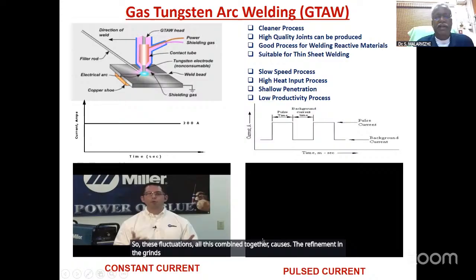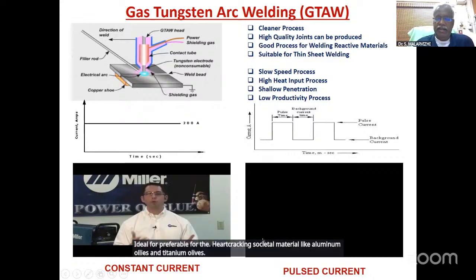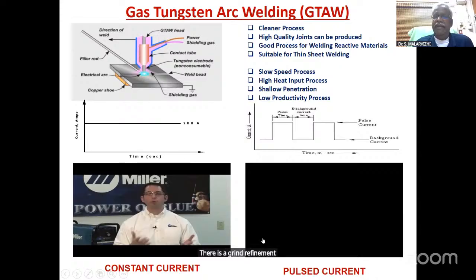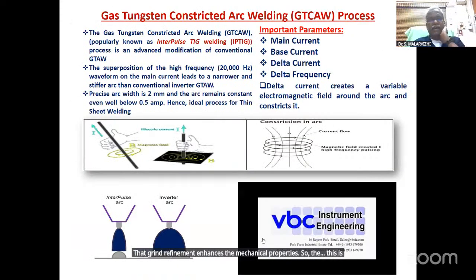So all these fluctuations combined together cause the refinement in the grains. Grain refinement is taking place in pulse current welding. This process is preferable for hot cracking susceptible materials like aluminum alloys and titanium alloys. A lot of work has been done, and it proved that grain refinement takes place in the weld fusion zone. That grain refinement enhances the mechanical properties. So this is about pulse current welding.